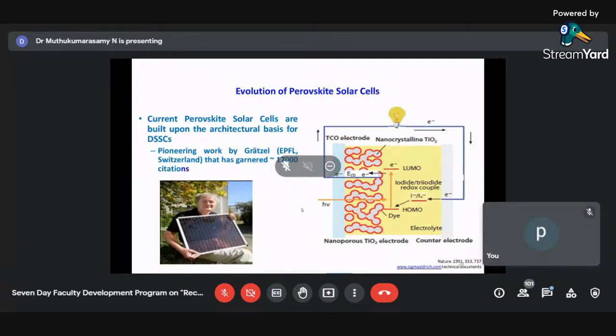Then you will be having your iodide type of material which will be used as an electrolyte. Then you will be having a counter electrode. So in the dye-sensitized type of solar cell, you have your counter electrode, TCO electrode, transparent conducting electrode, maybe FTO electrode. You have your nanocrystalline titanium dioxide material here, which has also the dye with it. So once light is incident, this dye captures that light, moves an electron from valence band to conduction band. That electron enters into titanium dioxide and moves towards the outer electrode. And the electron which the dye has lost comes from the electrolyte here, and it may be a polysulfide electrolyte or iodide, triiodide type of redox electrolyte. And from there you have the electron coming here, and the process continues, and you have electricity being produced. Electron starts to move through the external electrodes.